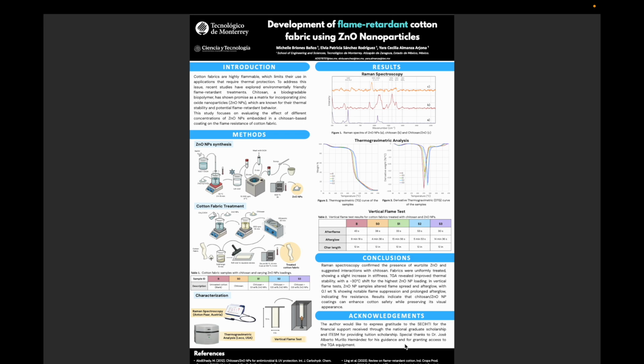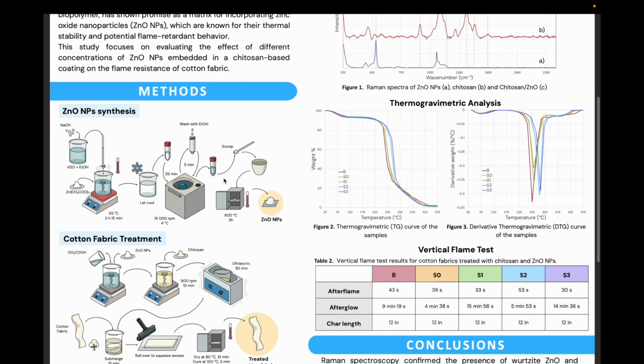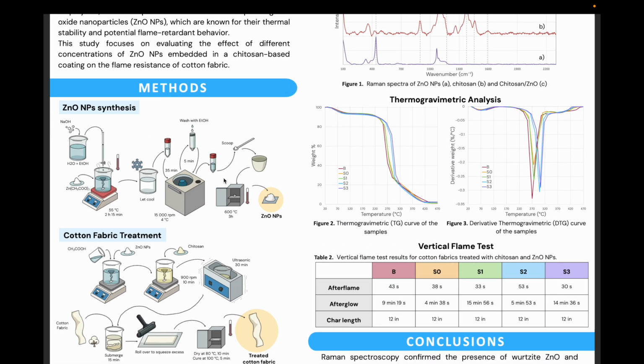Specifically, the objectives were to synthesize zinc oxide nanoparticles, apply chitosan zinc oxide coatings to cotton at different nanoparticle loadings, and characterize the treated fabrics using thermal, spectroscopic, and flammability tests. So, first, zinc oxide nanoparticles were synthesized by a precipitation method.